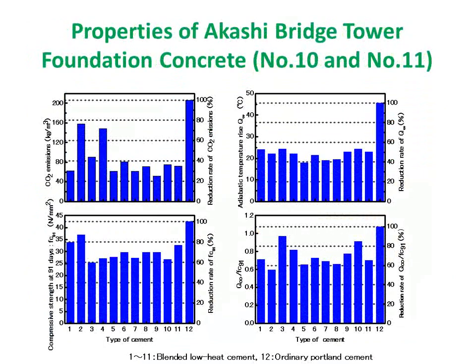And there are many developed cement concretes as shown here, from number 1 to number 12. Number 12 is the ordinary Portland cement, and number 10 and number 11, this cement was applied for the foundation of this bridge. And this is the carbon dioxide emissions, quite low. And this is the compressive strength. It's lower than the ordinary Portland cement concrete, of course. And then this is the adiabatic temperature rise. It's quite low compared with that. And okay, this is the fundamental property of this developed cement concrete.